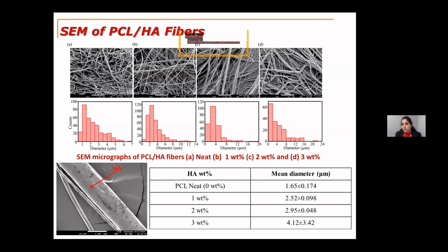Even for 1 weight percent and 2 weight percent, if we leave it for a longer time, they still get agglomerated at the bottom of the solution. However, when we increase the filler percentages, it happens so quickly. I should take out the solution from the thinky mixer or the planetary mixer and then inject it into the spinneret. Even in that time, these particles get agglomerated, within a few minutes, like 4 or 5 minutes. That happened particularly with the hydroxyapatite nanoparticles, because it has a particular tendency to agglomerate itself. Even if I crush it once and leave it for a while, it gets agglomerated after some time by itself.